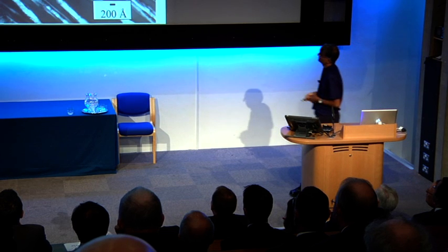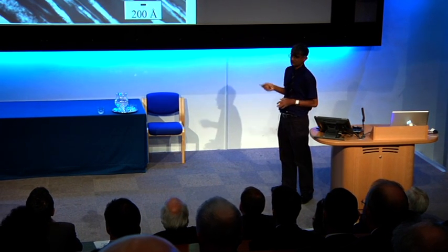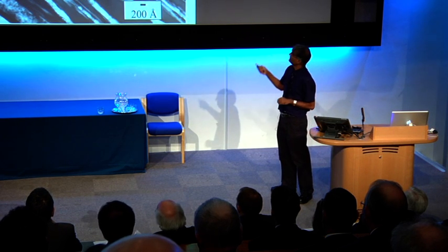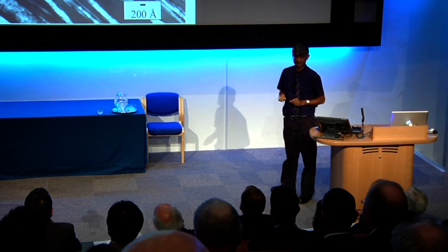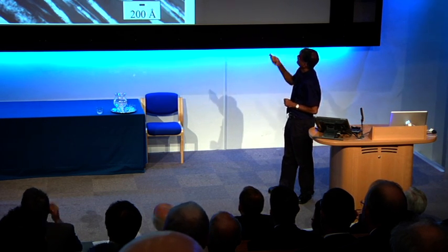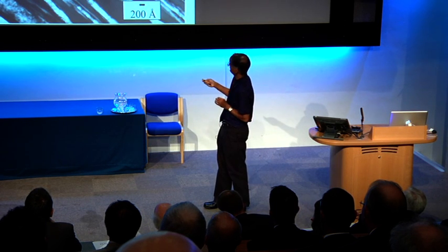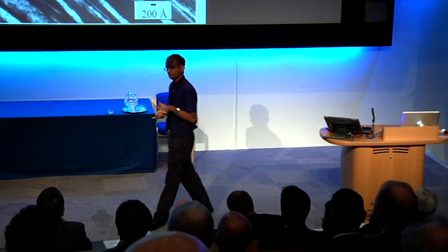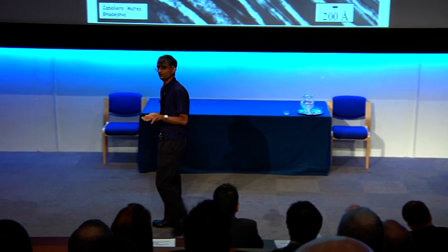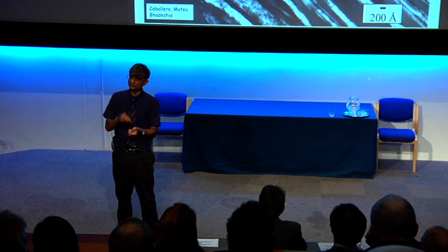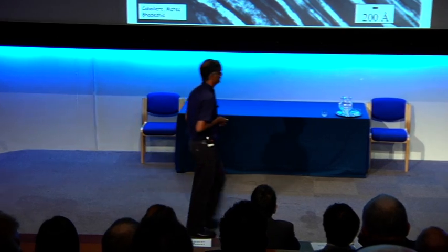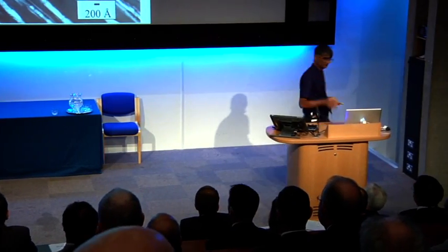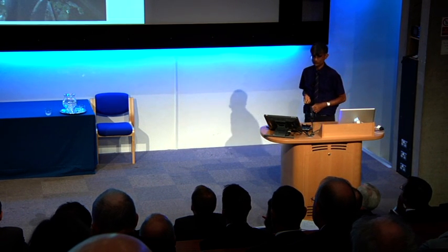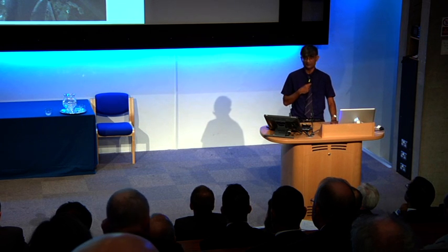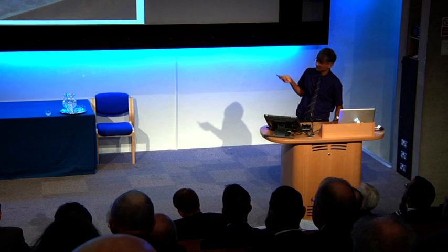This is the amazing structure that we discovered, where this is a scale which is in angstroms, but just to give you an idea, this is a carbon nanotube, which has made a lot of noise recently. These are crystals of bainite, which are finer than a carbon nanotube, and this is the austenite, which is dispersed between them. This material has the highest density of interfaces that has ever been produced in a bulk material. I'll show you what bulk means. It doesn't mean that you take a small amount of material and you bash it to produce a fine structure. So it's an exciting material. It's very, very strong, and it can be produced in huge quantities. So far, something of the order of 300 tons has been produced by Tata Steel. And it can be produced in different forms.